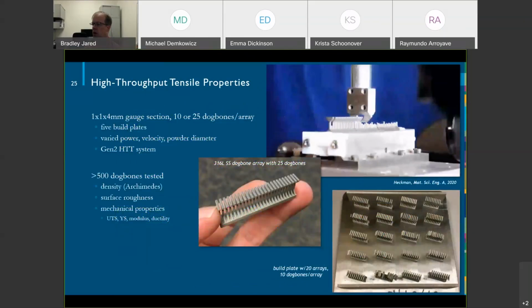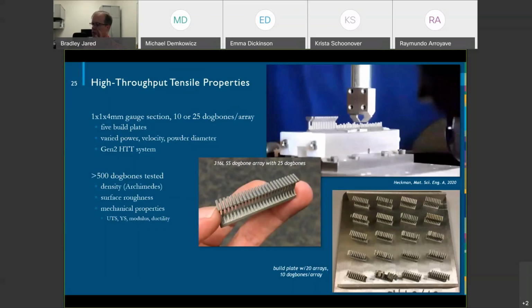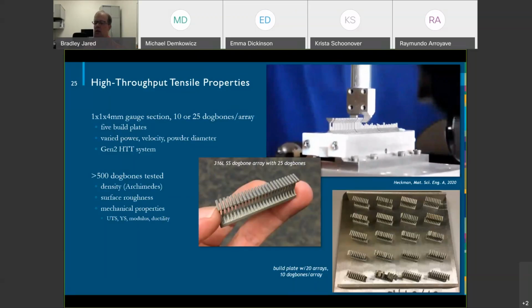So a lot of the data you're seeing here is actually from our Gen 2 high throughput tensile tester. When we started the Gen 1 work, we realized it worked extremely well, but we found that a bottleneck was the fact that we had to have somebody, a technician or even a student, loading samples by hand every minute or two. So what we did was we changed it. We added a linear axis to our load frame, and now we're using DIC from the side, not the front, and we're automating. I believe this will hold 50 or 75 tensile bars, so now we can load up a frame and a technician can walk away from it for an hour. And now we can start loading things at a much faster rate.